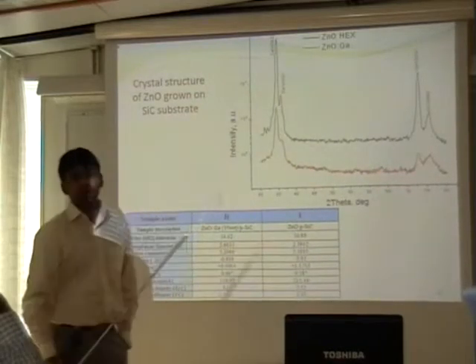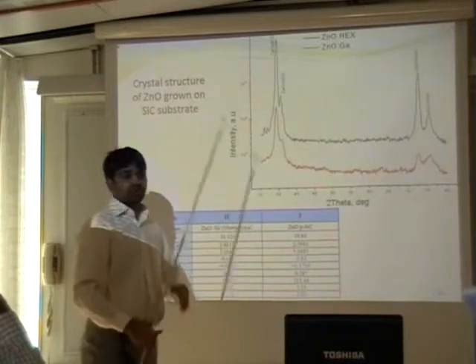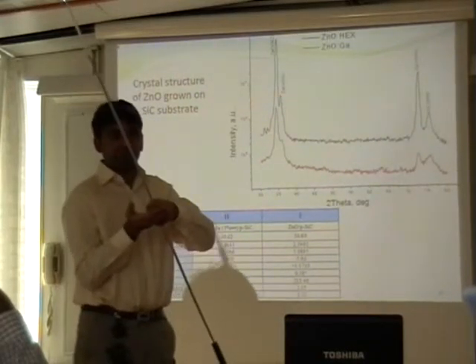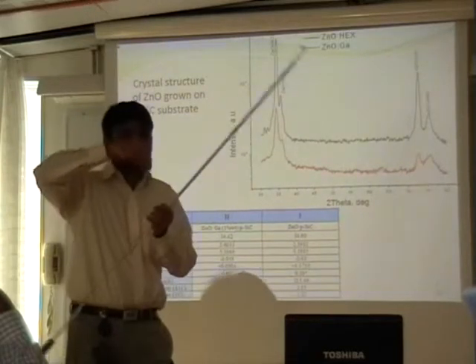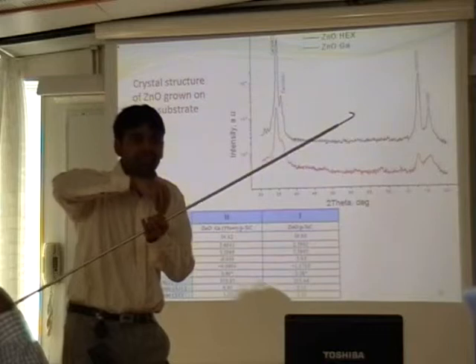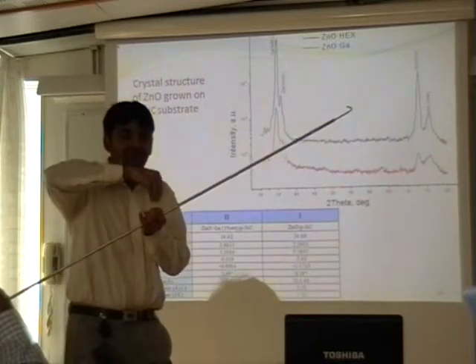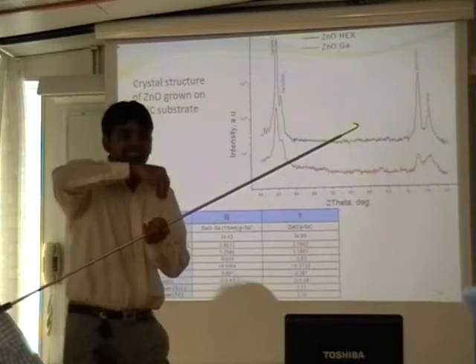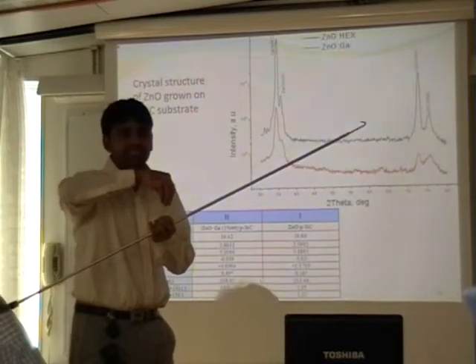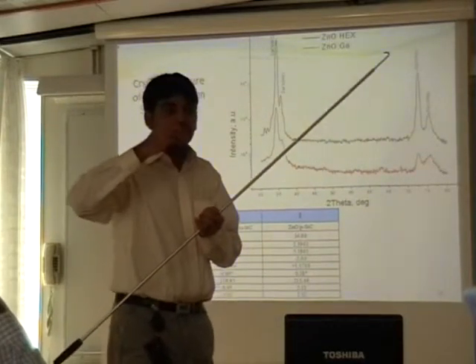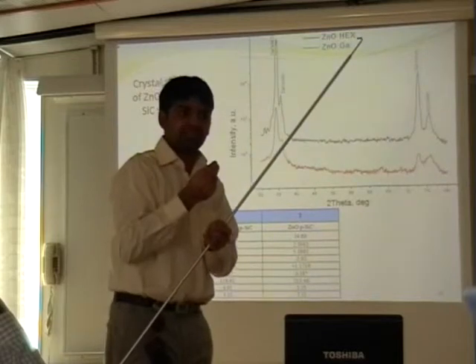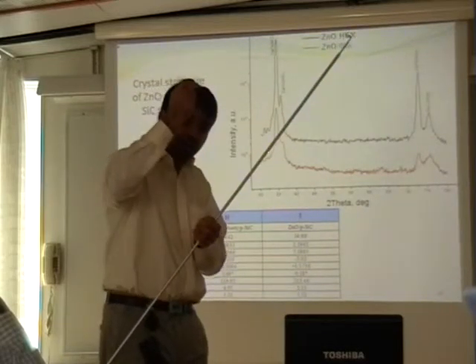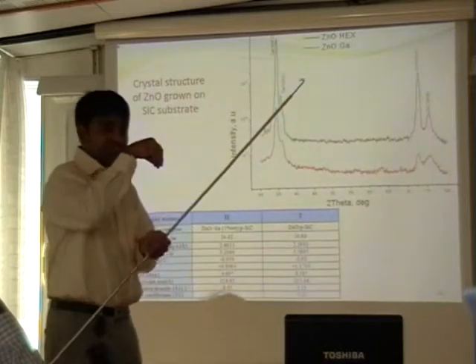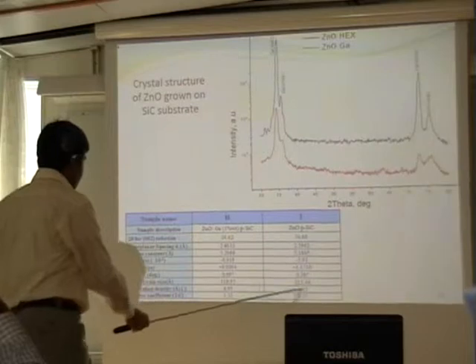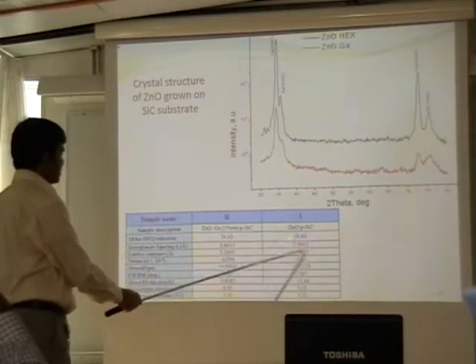except 2 short peaks. And here, due to the miscut of 8 degree, we believe that each zinc atom sits at the same place of the silicon carbide, and that film is not polycrystalline, that is the epitaxy film. Because during XRD measurement, we also increase the incident angle by 8 degree, so that all the rays are incident on the same place. And the texture coefficient will also increase, which the zinc oxide on a silicon.